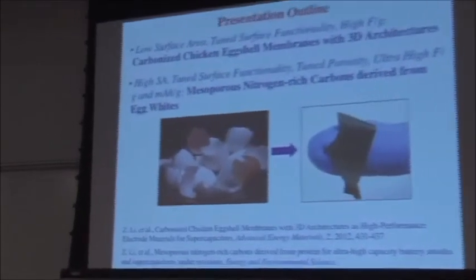In fact, probably one of the highest ever reported, and certainly the highest battery reversible capacity reported for carbon in terms of milliampere hours per gram. And that's mesoporous nitrogen-rich carbons derived from egg whites. So if we talk about the eggshell membrane, there's really only 2 processes that we used.